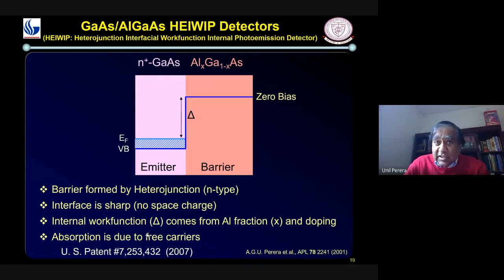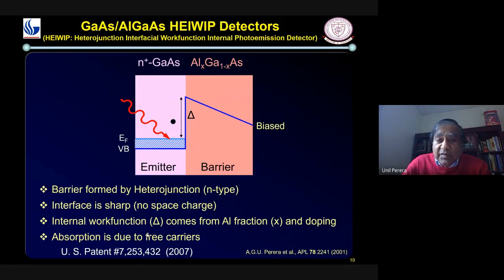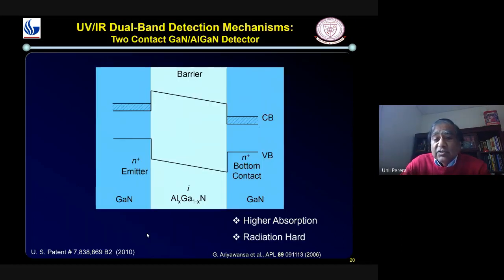So this is a device structure, heterojunction, emitter and barrier. I'm only showing the one band of that. So this is what is called the inter-subband or interband. When you apply bias voltage, so this is zero bias, flat. And if you apply bias voltage, the bias drop is across the barrier because it is not doped. So now if you send infrared, the carriers will absorb the infrared photon and go through, and that gives you a current. So this is a photocurrent coming through because of infrared. So that is a detector. This is N-type, but this can be used for P-type too.